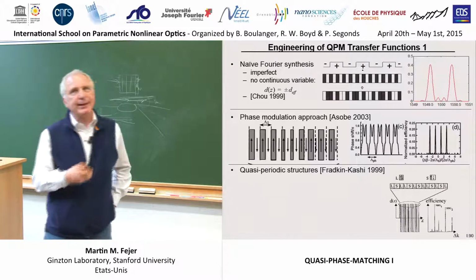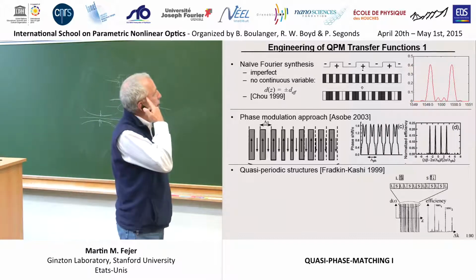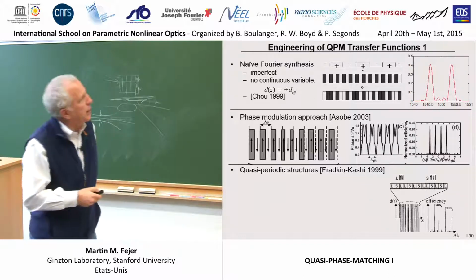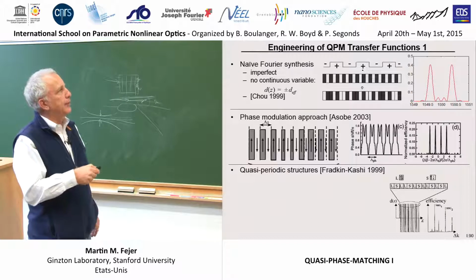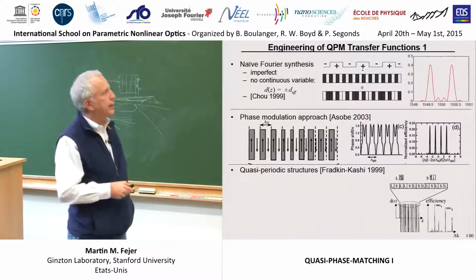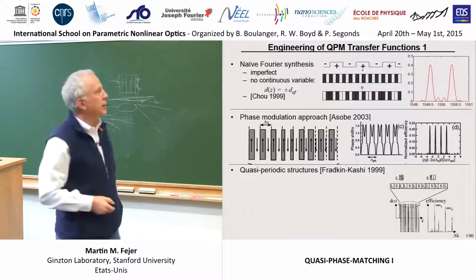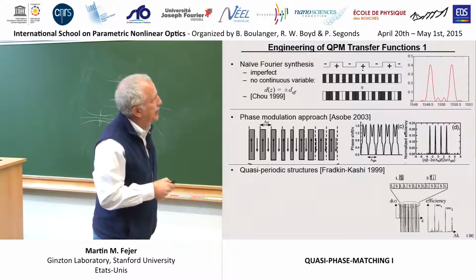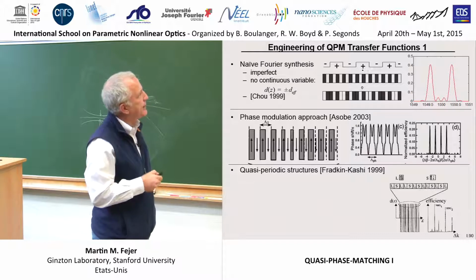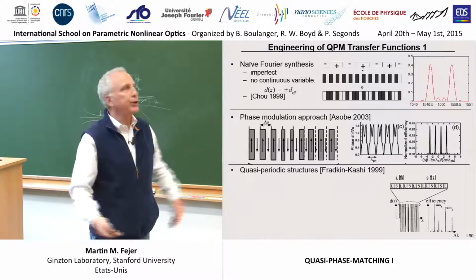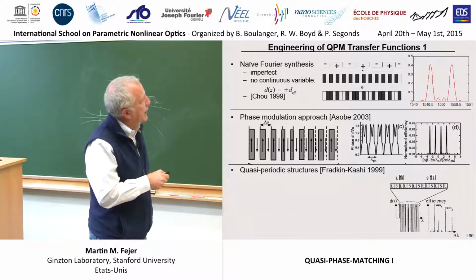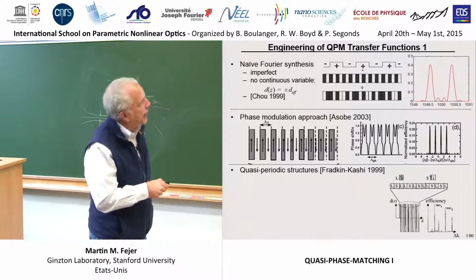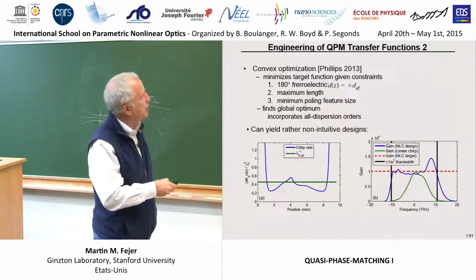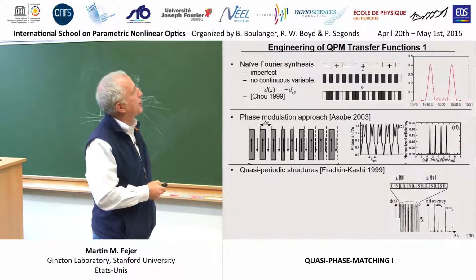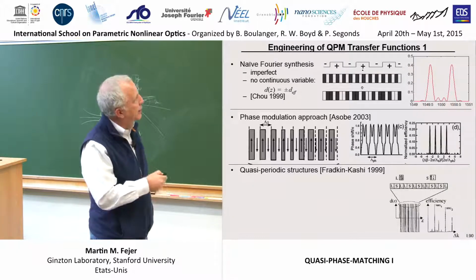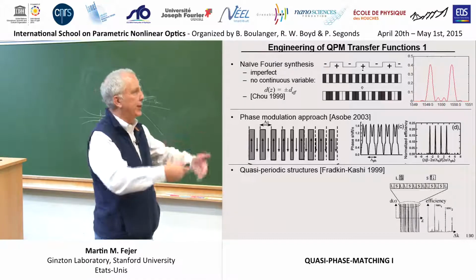So what kind of techniques exist for doing this sort of engineering? The most naive approach, and hence the one that we thought of, not the best approach, is you know that if you take the product of 2 sinusoids, forget that these are square waves for a minute, you get some difference frequencies coming out, right? So you can make a single peak split into 2 whose separation is set by what this other frequency you're multiplying by looks like. And so if you took this pattern times that pattern, you would end up doing some more complicated domain reversal pattern that looks like the product of 2 sine waves, and you can split this thing into 2. If you put another sinusoidal component on there, you could get 3 or 4 or whatever.